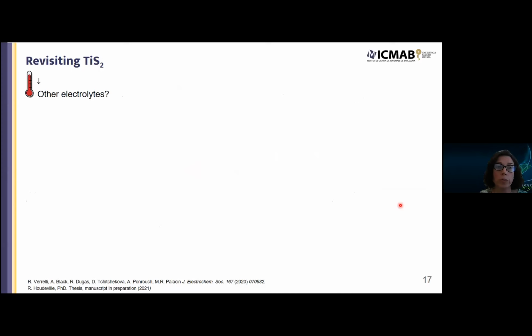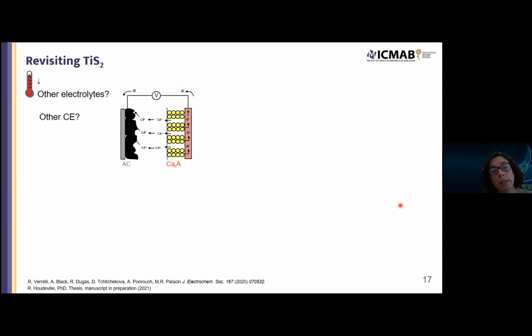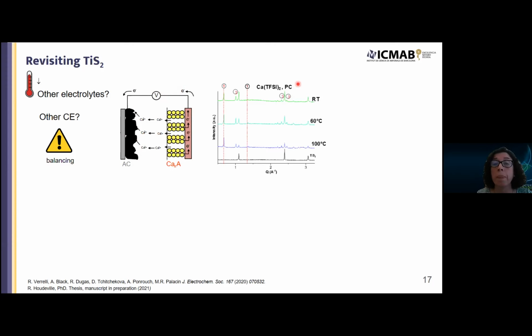So at this moment, we were thinking of separating issues and just not importing problems of calcium anodes when looking for cathodes, and trying to decrease the temperature, because testing at 100 degrees is also a guarantee of electrolyte decomposition. So we were looking at other counter electrodes, and the first obvious choice is activated carbon, and this is what we did. The main issue here is that the balancing of the cell needs to be carefully addressed, because the capacity of activated carbon is very small due to the capacitive mechanism, but still, if this is taken care of, one can have successful results. And this is what we did.